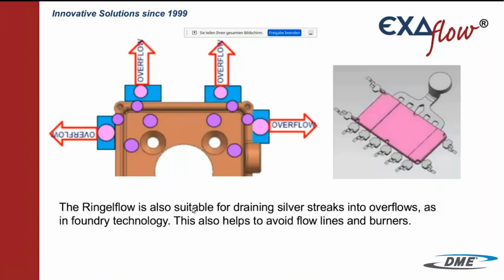So what also is a great idea is to produce overflows in plastic. Yes, in a plastic injection mold. So I know this from casting. And here on the right side, this picture is casting. So here we inject the casting, maybe aluminum or something else, or zinc. And what we here see, these are all overflows. I remember many customer problems with silver streaks. So if there is a silver powder inside of the plastic to make it look like metal, and where the plastic flows, you see then the silver streaks. And with the overflows, you can make a direction where this material goes.